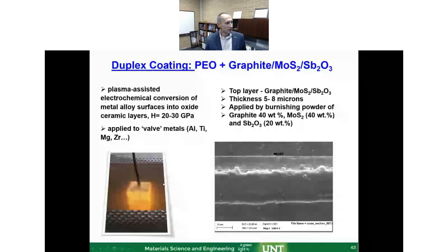overview: you need to have an electrolytic bath, for which you put potassium silicate solutions, and you use aluminum or titanium or some of these what we call valve materials to make a part, and put it inside of the electrolyte. You're using high voltage pulses, and you break the electrolyte, so you initiate a micro arc sparking on the surface. So you can see the glowing in here, this micro arc.